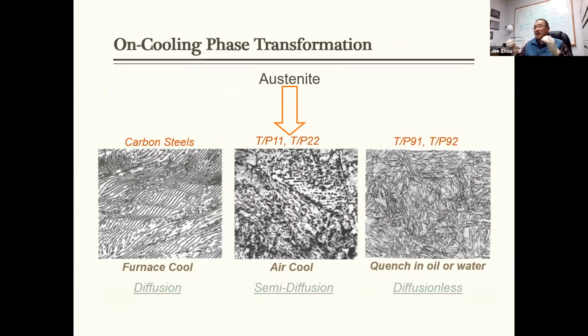for the continuous cooling transformation, as I said in the past, we control the cooling rate. When we control the cooling rate, then we control the precipitates. So in the carbon steel, you see all the precipitates are lamellar. When you're cooling down, everything is already formed. So if you do the tempering on that, you are not going to change the structure very much. You are making it degrade slightly.